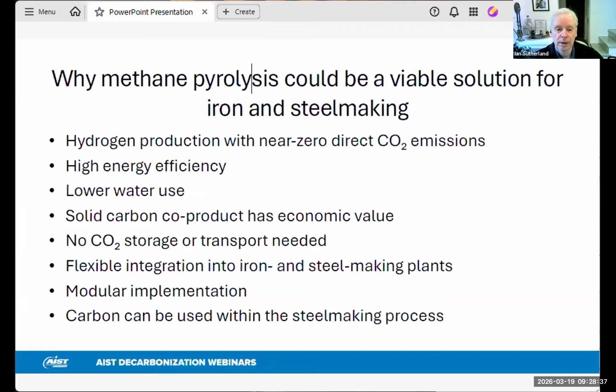Other benefits of methane pyrolysis is that the process does not require captured carbon dioxide to be transported or stored. There is flexibility in where the system can be located in a plant, because it just needs to sit close to a supply of natural gas. Also, the system can be designed in package sizes that enable a modular incremental implementation strategy to be adopted. And also, interestingly, the carbon co-product can also be used within the steel making process.